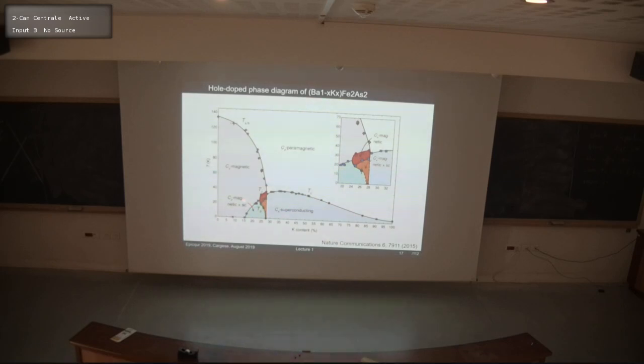And as I mentioned earlier, concerning your questions, deep inside the superconducting phase, new phases have been discovered where the system seems to recover back its tetragonal C4 symmetry once inside the nematic state, inside the superconducting state. So that's telling us that there is a strong competition between what type of magnet is stabilized and how that competes with the changes in structure and potential different type of magnetic orientation, especially of the spins from being in plane to potentially switching towards the c-axis.